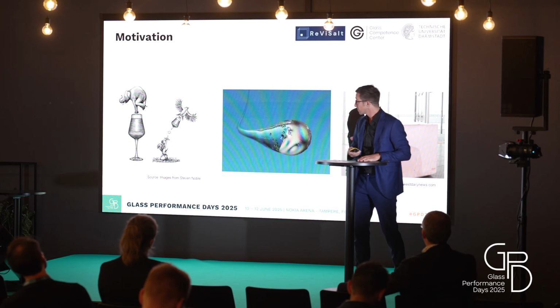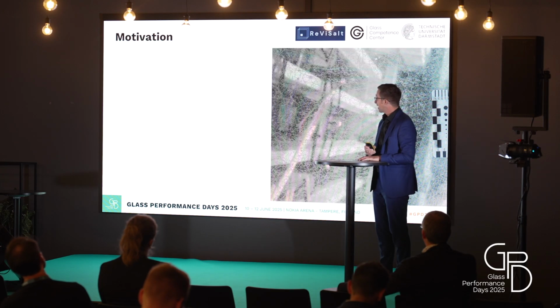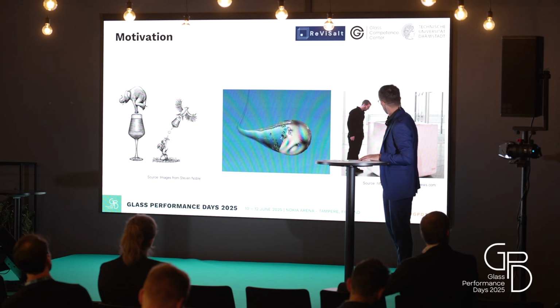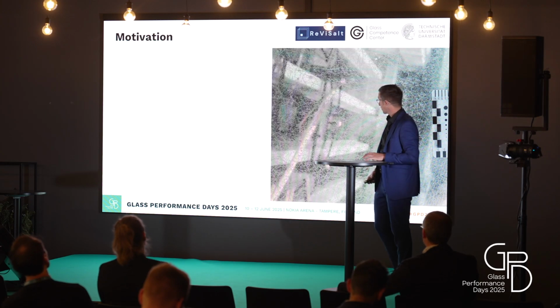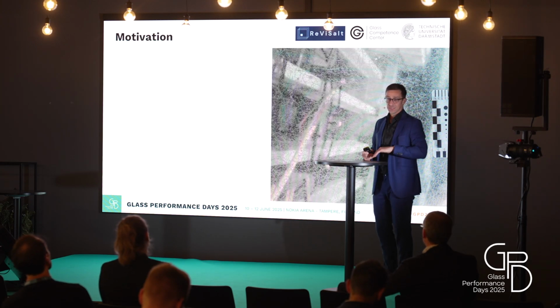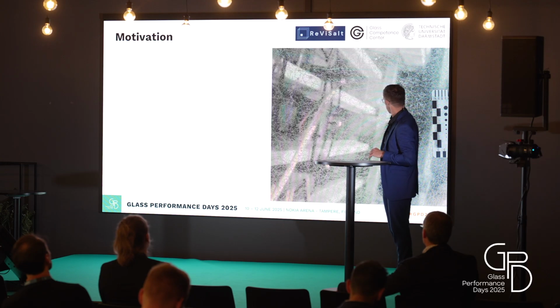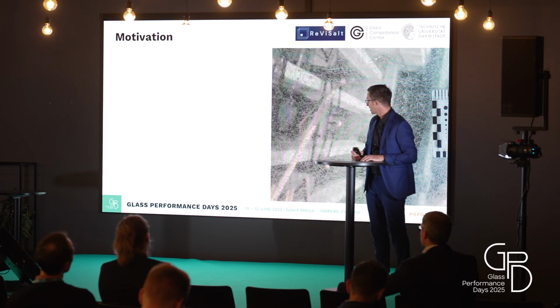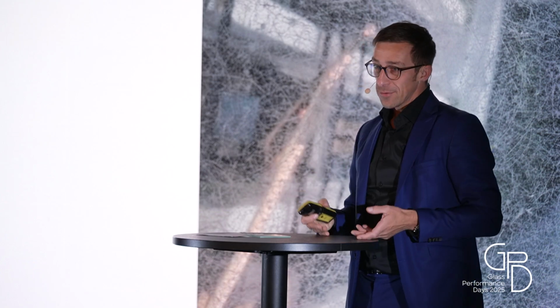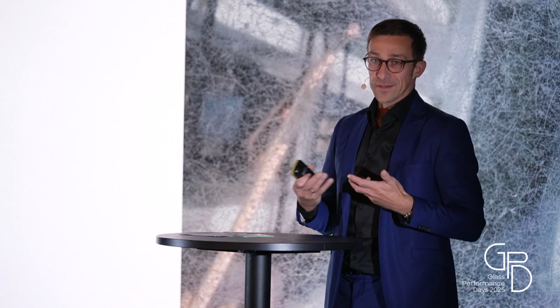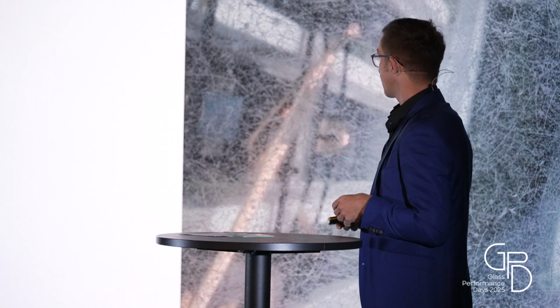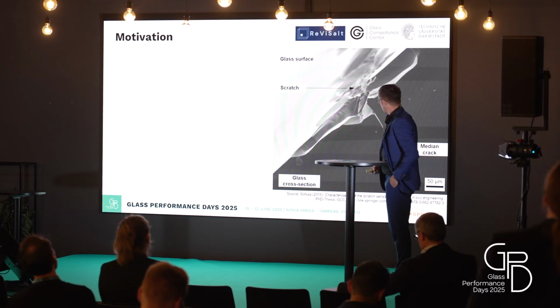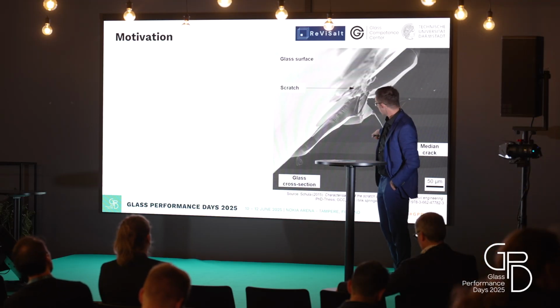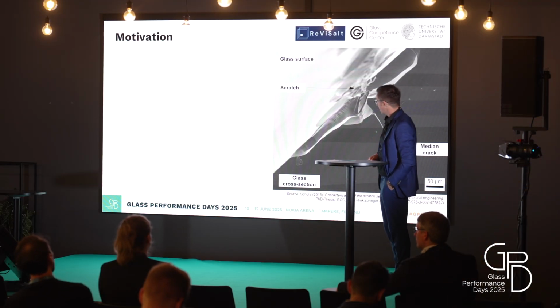We can avoid this. Then we had not only cracks in such big glass cubes, we also had some cracks in such walk-on glazing. You can see here in a church in Arnhem. And we know that the strength of glass is, more or less, the quality of the surface. There are a lot of cracks in the surface. Here you can see under the microscope.